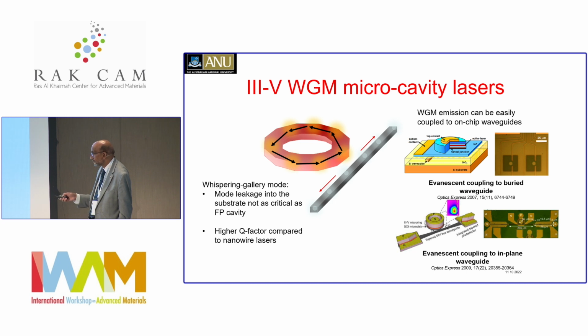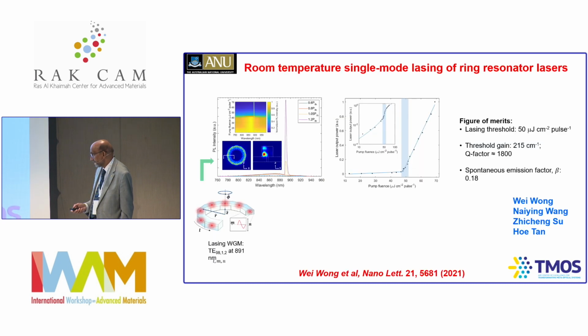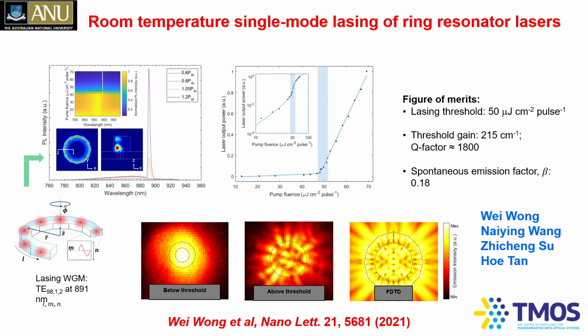That's what we're working towards, for example. Again, Wei Wong has spent a lot of time during his PhD designing what the diameter of the ring should be, what the height of the ring should be, what the width of the ring should be. Based on those simulations, he has grown these ring resonator structures. Then he excites them with a laser pulse and looks at the light emission.